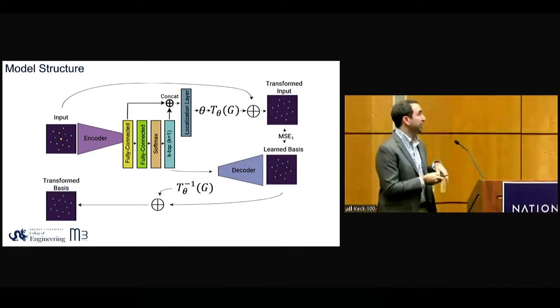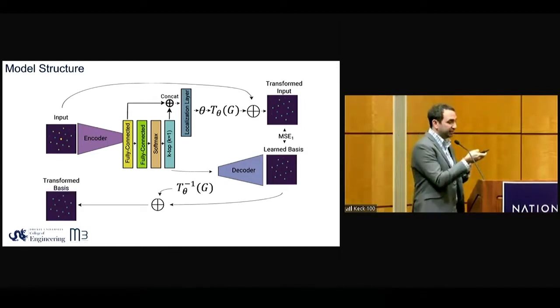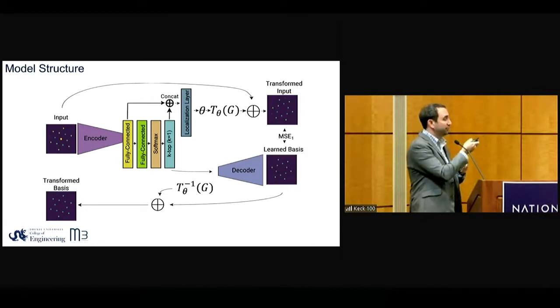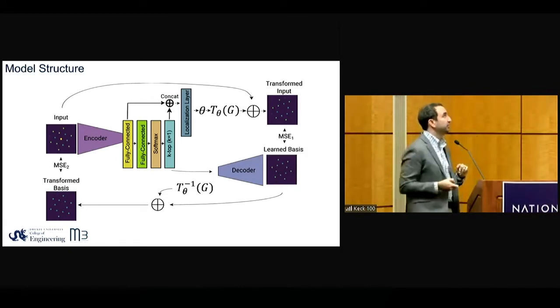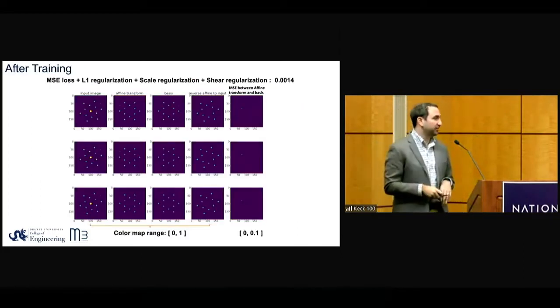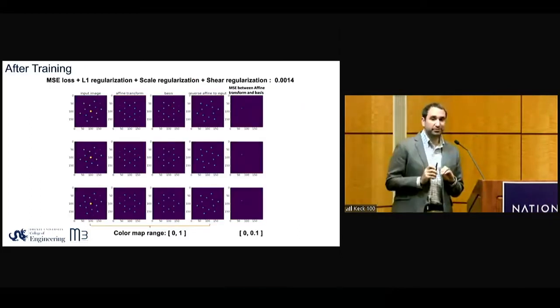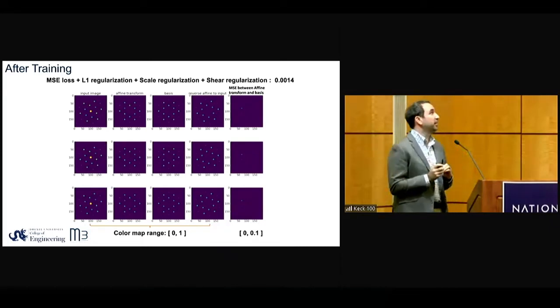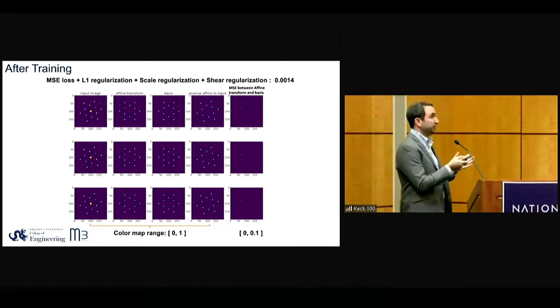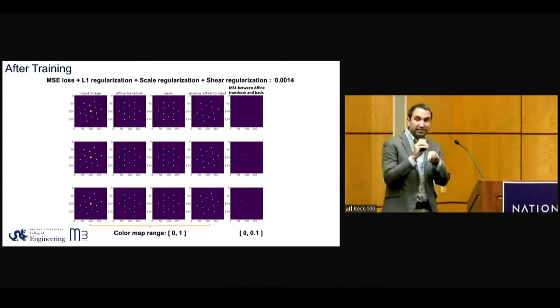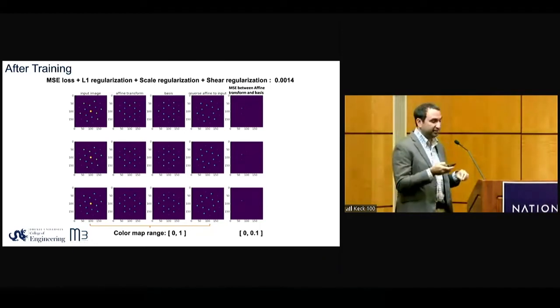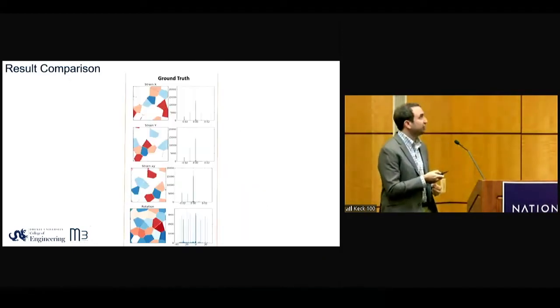To help the training, we train it cycle-consistently. We take the inverse of the theta matrix, apply the inverse affine transformation, go back and also compare it to the original. That just solves some problems. With the right tweaks in terms of regularization strategies added to the model, we can get really good reconstruction. So, let's say the dots all line up, which is good. That's a good sanity check.